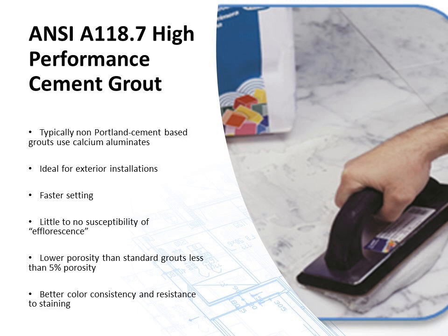They're ideal for exterior installations. Faster setting. Little to no susceptibility of efflorescence. Efflorescence is water-soluble alkali that comes out of Portland cement. And if there's no Portland cement in there, it can't come out of the grout.